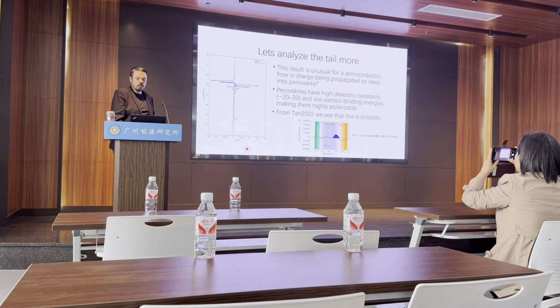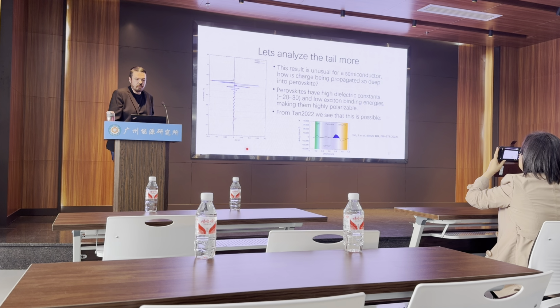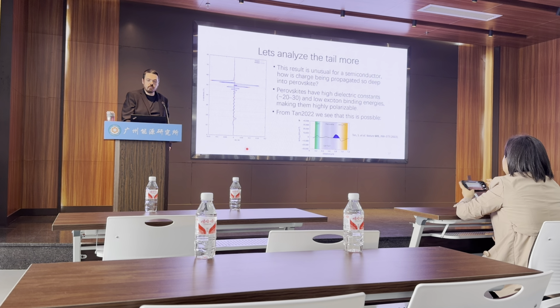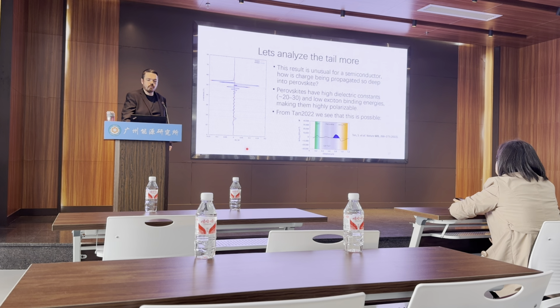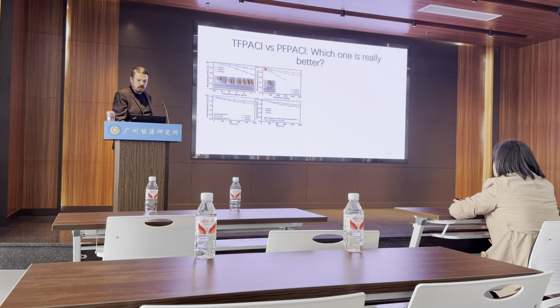So this result, as I said before, is unusual for a semiconductor. How is charge being propagated so deep into the perovskite? The reason is perovskites have high dielectric constants and low exciton binding energies, and they're very highly polarizable, so it checks out, and the experiment also checks out. So this is reasonable. This result in general is fine. This is probably pretty close to experiment.